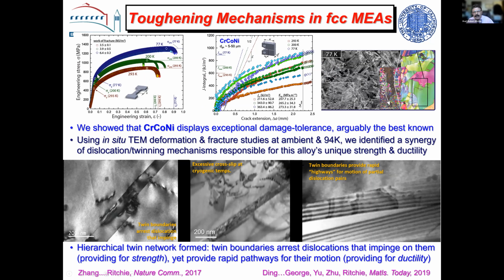They don't have a great yield strength, by the way, but they have very high tensile strength. But we're getting 90% tensile ductility at liquid nitrogen temperatures, which is remarkable. Now the toughnesses are really high. The initiation toughnesses go from 200 to 273 megapascal root meters at liquid nitrogen temperatures. That's extremely high. And the crack growth toughnesses, what I call the steady state toughnesses, are up above 400 megapascal root meters. Now these are really big numbers.